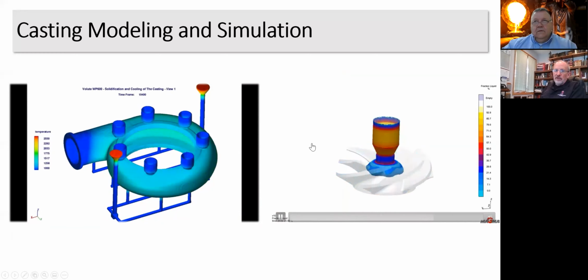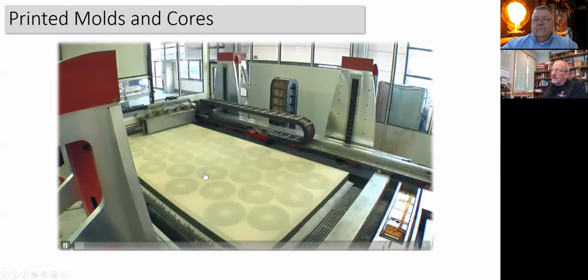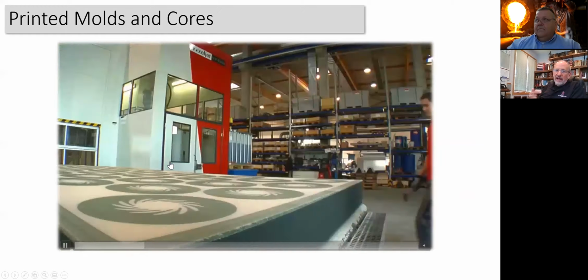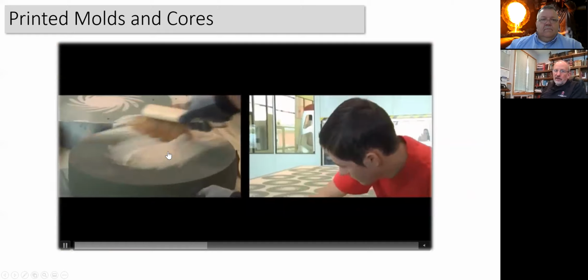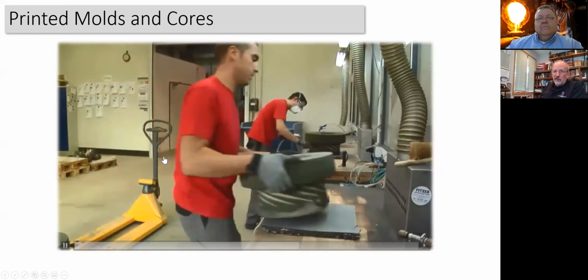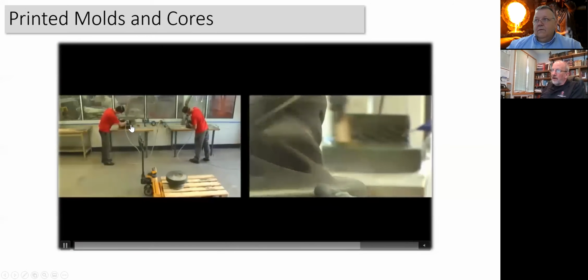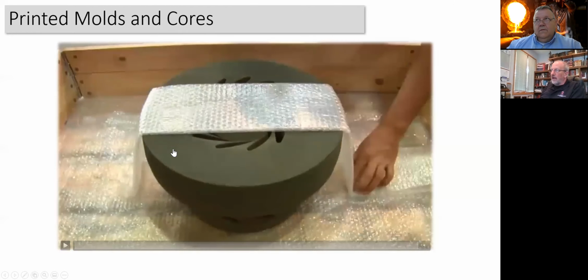We really have been some of the early users of additive manufacturing. We were the first adopters as foundries. So one of the things we do now is we print the sand cores and molds that allow us to make really complex shapes without having first to buy a mold, a pattern, or a die. This allows our modern customers to try 4 different designs at the same time without having to buy tooling first. And it allows us to make really complex shapes that would require 5 and 6 cores and would be difficult to make dimensionally accurate. We can make them accurate.